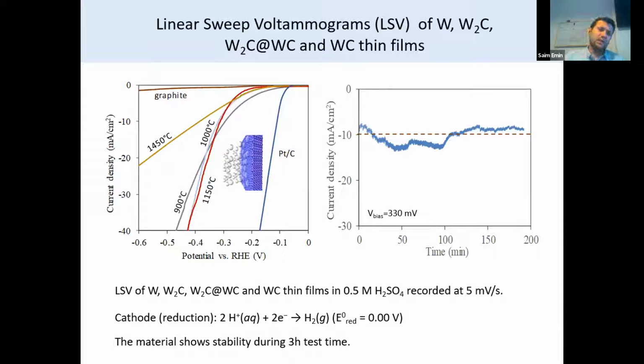On the left side is this current-potential plot. The current is a result of hydrogen evolution, and if the current starts close to zero potential and increases steeply, it is better. As you can see, platinum is much better than the other films. However, our study was a conceptual study: how we can go from metallic tungsten to produce carbides, and after that use these carbides in hydrogen generation. On the right side is a plot of hydrogen evolution at fixed potential.